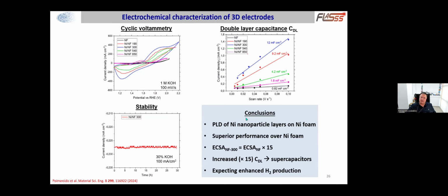And concluding, we have applied and employed basically pulsed laser deposition of nickel nanoparticle layers on nickel foams. And we have found a superior performance in their electrochemical characteristics over the nickel foam, an increased electrochemically active surface area, and also potentials for use in supercapacitors.